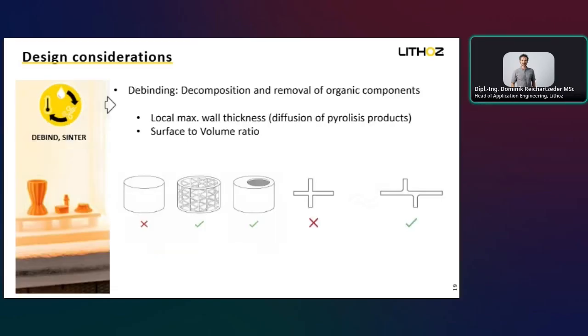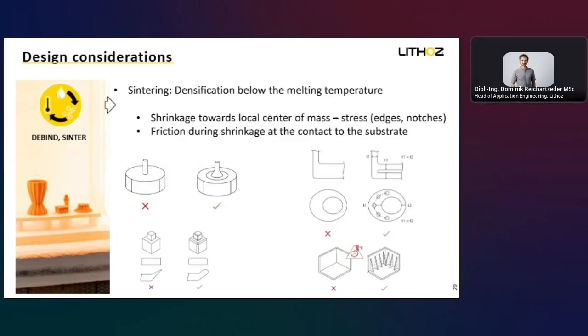As explained earlier, the polymer gets decomposed thermally during debinding, and the decomposed products must diffuse out of the part. Having a low wall thickness and a high surface to volume ratio makes this step faster and easier. The densification of the ceramic particles during sintering to the final properties involves, as mentioned earlier, a significant amount of shrinkage, which needs to be considered. Edges, corners, notches should be chamfered or smoothened, and the wall thickness distribution should be homogeneous to avoid stresses.